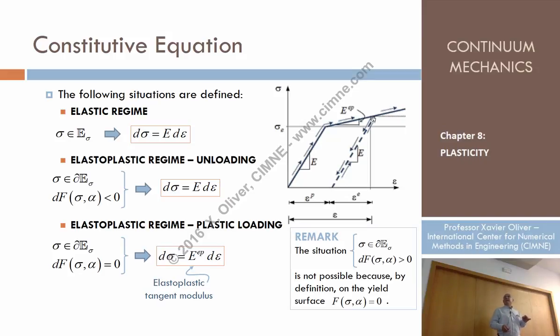But now the evolution of the problem takes the stress to decrease. The increment of the yield function is smaller than 0. And that means that the point is going to become elastic. It's going to enter into the elastic domain. So it's what we call unloading. Graphically in that plot, we are just here, but now we unload. We are moving, but decreasing the stresses. We are entering into the elastic domain. That is what we call unloading.